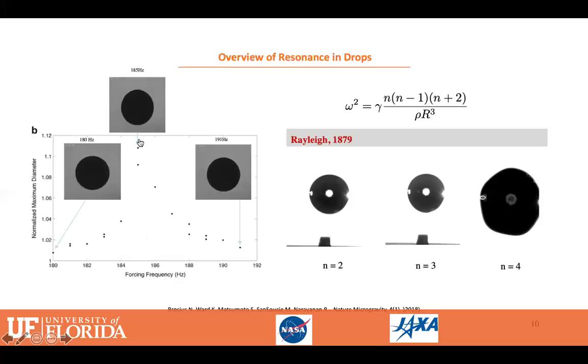Having noted this frequency, which is now the natural frequency, we introduced this into a formula derived by Lord Rayleigh. And you can see from this formula that the frequency squared is related to a number of quantities. The first is the surface tension given by gamma. It's also related inversely to the density of the liquid metal and the radius of the sphere when this drop was once a sphere. So from this natural frequency, we can determine the surface tension once you know the mode into which it excites, which you can see visually. This mode, which you're seeing on the left, corresponds to a bimode, and that corresponds to this integer in the numerator of this formula, little n equal to 2. So little n equal to 2 implies it goes from prolate to oblate.